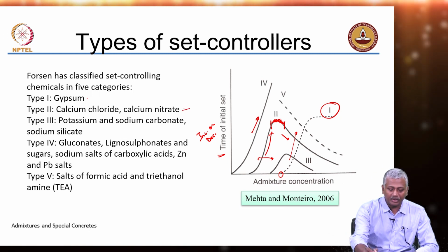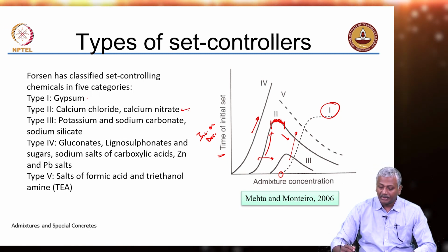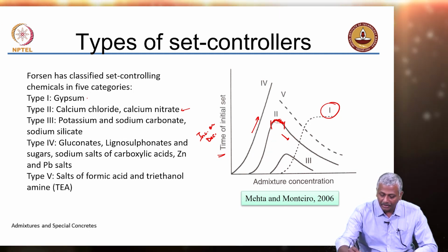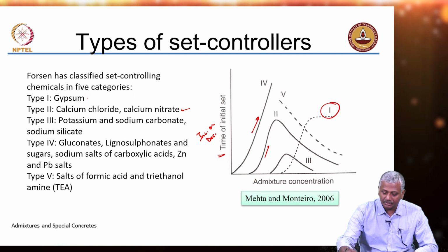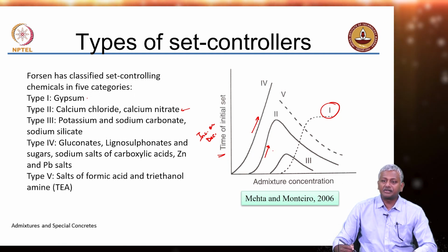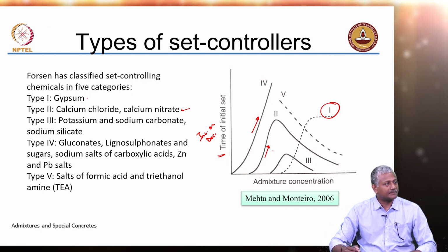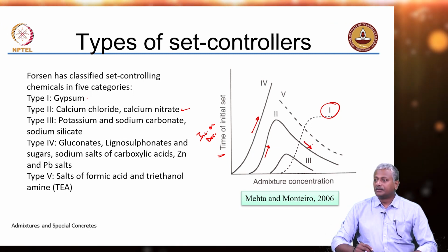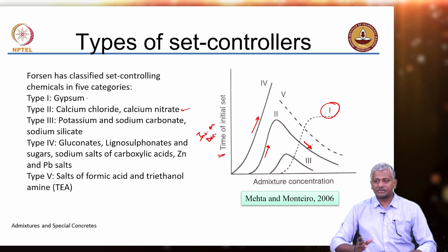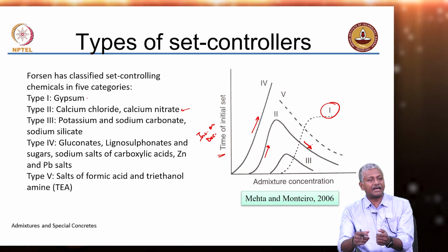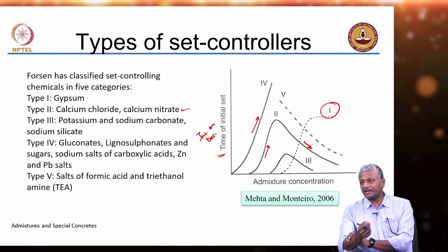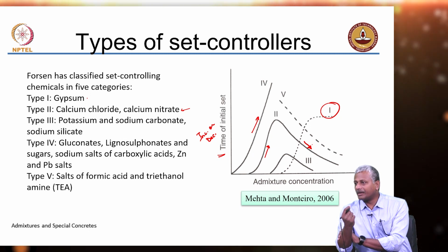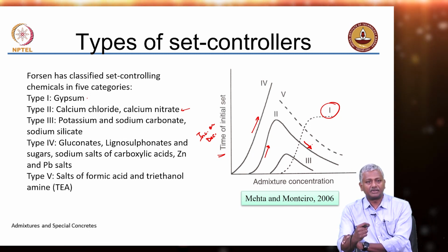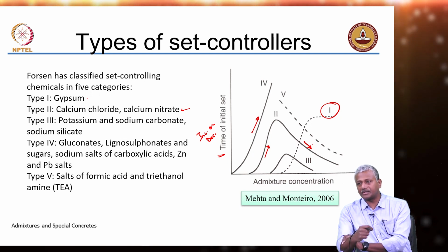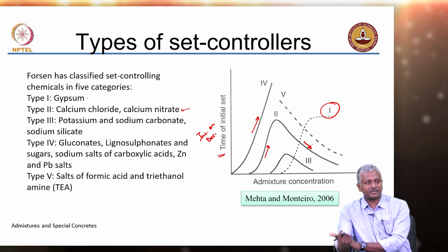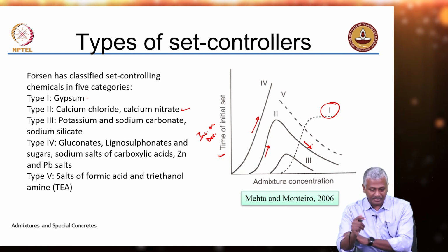Type 2 is calcium chloride and calcium nitrate, which are well known as accelerators, but interestingly when you look at these accelerators, you see that there is a dosage of these chemicals where the set time is actually increasing, and there is a dosage where you get the acceleration. What does this go to show? This tells you that this chemical has opposite effects at different concentrations. So, you need to be very careful in designing the concrete mix with the right dosage of the chemical. At too low a dosage, you are leading to retardation. At high dosages, you are causing acceleration. So, you need to ensure that you have high enough dosages present of the system.